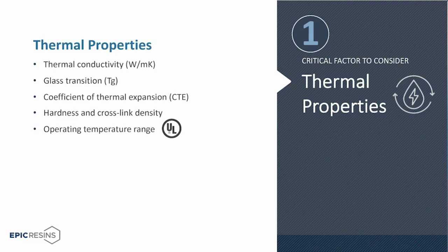A third property is coefficient of thermal expansion. Now this is the rate of expansion over a temperature range. We evaluate TG and CTE using a thermomechanical analyzer, also termed a TMA. This measures the height of a sample when ramped through a temperature range. The image we are showing here is the graphic result of a TMA.